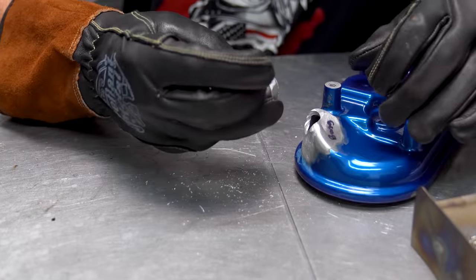Well, the answer is actually right in front of you as you're welding. There really are no settings for cast aluminum. Settings are for microwaves and TV dinners. You just have to find that sweet spot. If you can see a nice weld pool like what you see on the screen here, then you're just right. Notice how the weld pool is actually contained in a certain spot, and as I move the torch around, the weld pool follows with it. If it was one gigantic weld pool and everything starts to melt down, then you're obviously too hot. If the weld pool is not even a pool at all and the filler is just balling up and sticking all over like solder, then it's obviously way too cold. You just got to find that sweet spot and be able to read and adjust as you go.